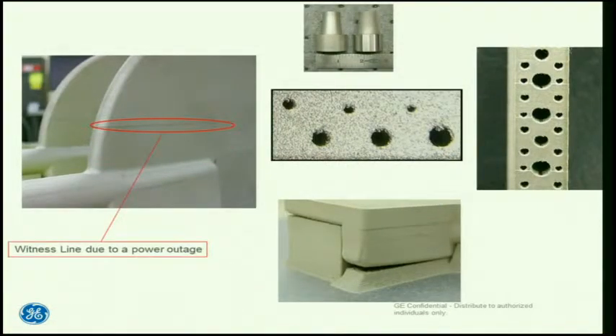For instance, you get a witness line on that rake when you have a power outage. Why does that happen? Can you still use that part? That happened because of a power outage. The machine was down for probably 8 hours until we came back in. It happened in the middle of the night. But when you restart the machine, you have metal shrink and you start sintering on your next layer and you have this witness line. So we did some testing and we felt pretty confident that with the right restart procedures you can keep going. However, we would never do that for a critical component, and we would always have to get the permission of the engineer and designer that we were about to do that, which in essence meant we started over.